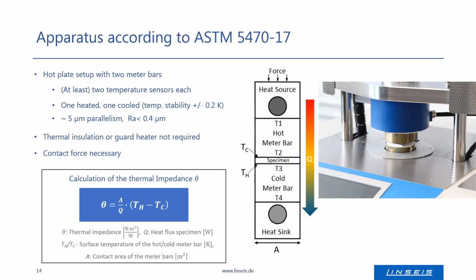One of them is via two meter bars with a heated and a cooled meter bar. If this principle is used, a guard heater and a thermal insulation is not required, and the heat flow through the specimen is computed as the average heat flow through both meter bars.